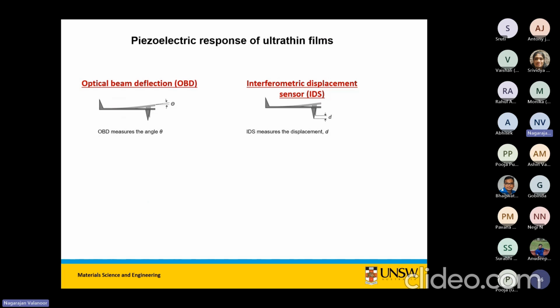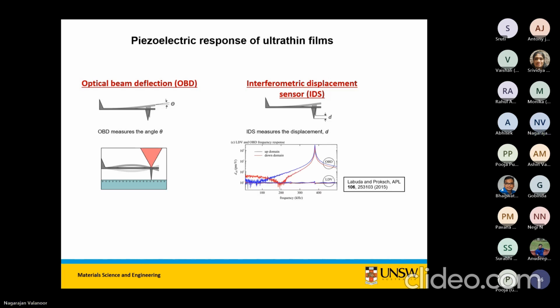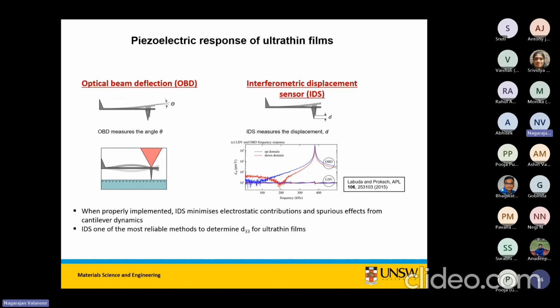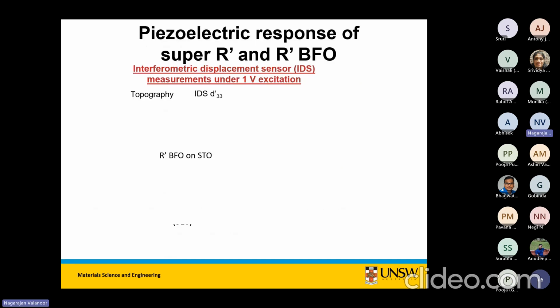Okay, so we sent a student and a sample to Oak Ridge. They got really nice data, and we know that the displacement measure is very accurate, a lot more accurate than the normal method of PFM detection. This was important because we were claiming that our piezoelectric coefficient is very high compared to normal BFO. So if you want to claim something like that, we got to absolutely make sure it is really high and there are no spurious effects. So we do get that.